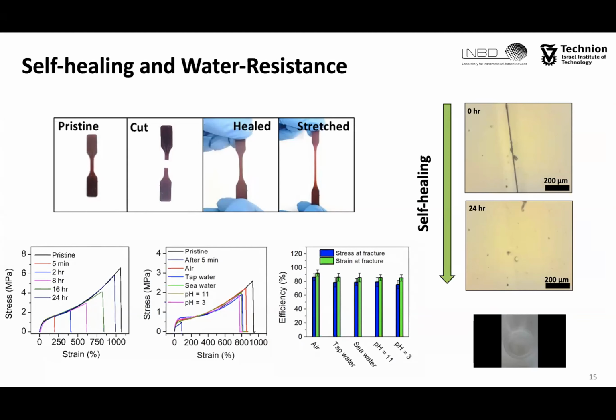The results on the screen show that the self-healing efficiency under all aqueous conditions was comparable to the healing observed in air. This water-insensitive self-healing capability originates from the highly hydrophobic, water-resistant repeating unit of the polybutadiene, which we introduced into the polymer.